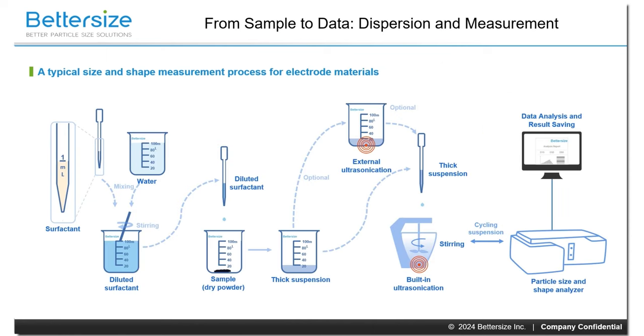Before we take a look at the Bettersize customizable report, let's see how a measurement can be made. Here we can take graphite as our example. As we know, it is a kind of black dry powder, not soluble in water. But one thing we should consider is that most graphite samples are not so wettable. This means if we directly pour dry powders into water, or vice versa, they will float on water but not forming a suspension. To do the test in ideal dispersion status, we should do some pre-dispersions, such as adding diluted surfactant or using external ultrasonication.